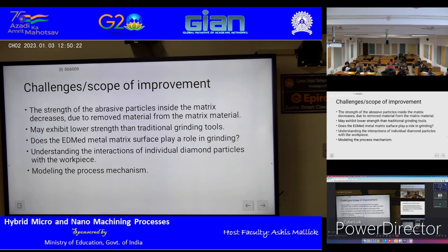Challenges. One of the challenges is, remember, you are removing the binder material, right? So some of the diamond particles may loosen, and when you are machining, they can come out, right? That's a challenge, especially when you are trying to go too small. Or you see one of the authors tried to get a very sharp 5 micron tip. Sometimes the particles will be loosened, and if the particles are not there, then what happens is rubbing of the metal matrix instead of grinding, right? You have those fine abrasives that do the grinding process, but if the fine particles are not there, you are just using a metal piece. It is mostly a rubbing action, right? So that is something that has scope for improvement, okay?